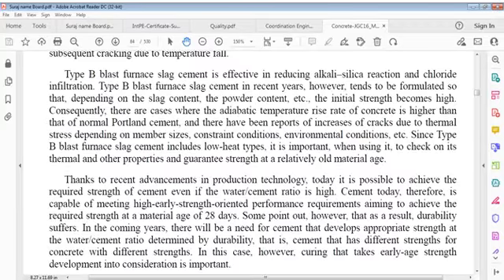In other words, through an analysis of cement content and final setting time of concrete, behavior of adiabatic temperature rise history can be predicted. And the conclusion is, effects of cement content, placing temperature and setting time on adiabatic temperature rise history in concrete were investigated. Conclusions drawn from this study are as follows. It is found that maximum adiabatic temperature, maximum value of adiabatic temperature rise, that is K, and reaction factor R have a high correlation with cement content, excluding admixtures of unit binders content. It can be considered that cement content in concrete mixing is an important factor to analyze properties of adiabatic temperature rise.